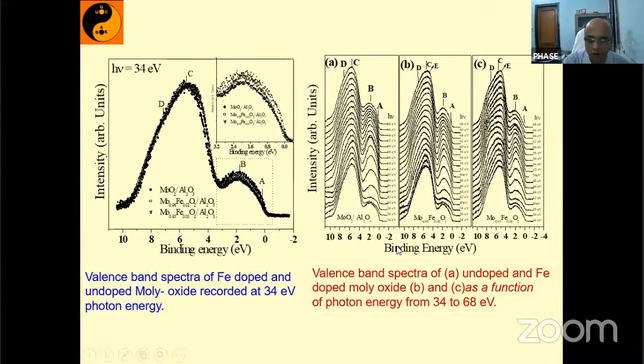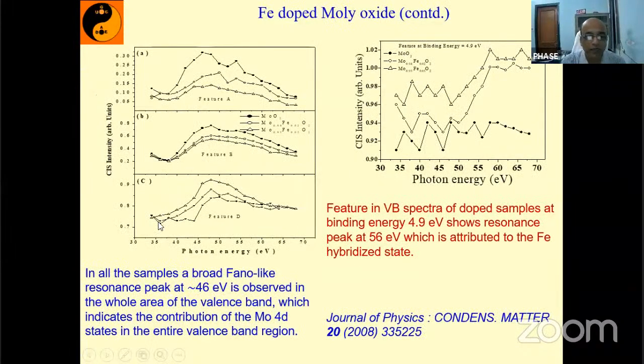So this is one of the papers by our student. He has done the analysis as a function of energy, to see what is happening to the different peaks. And finally he found a peak around 56 eV photon energy, where he found that the iron level is matching with this 56 eV. And that's why the iron is not only sitting as an isolated cluster inside the molybdenum oxide, but it is interacting with the molybdenum, and it is forming a compound with the molybdenum. So that is the conclusion of this paper. This is the kind of experiment one can do using synchrotron-based photoemission spectroscopy.